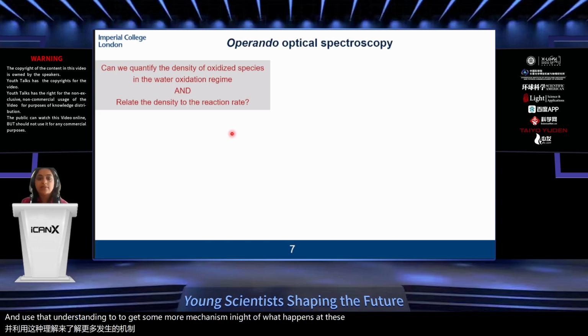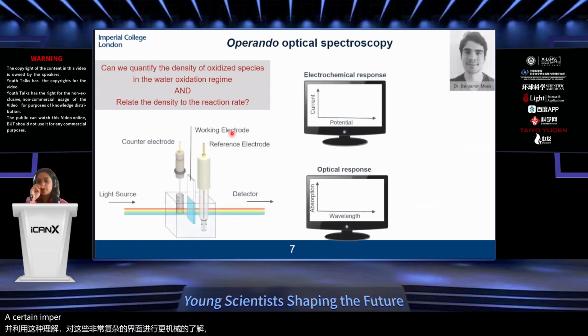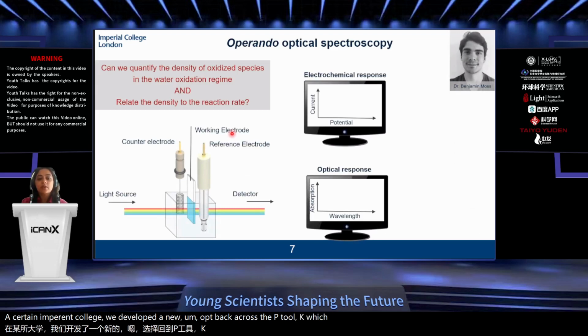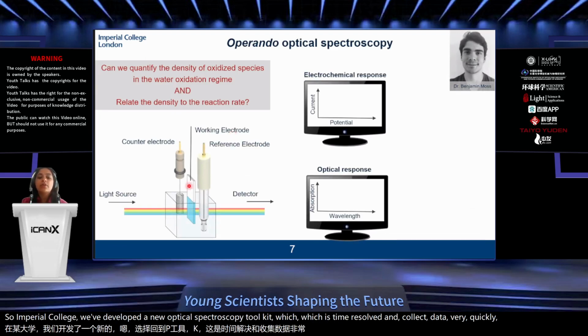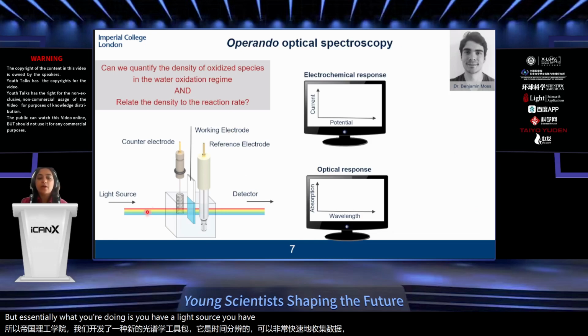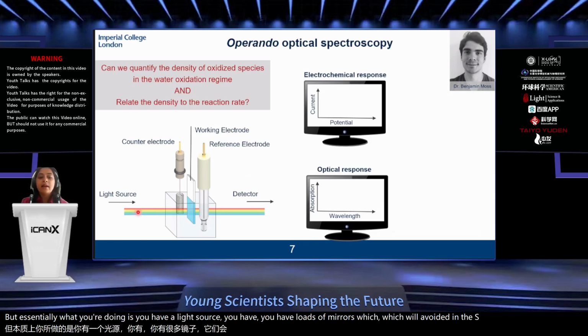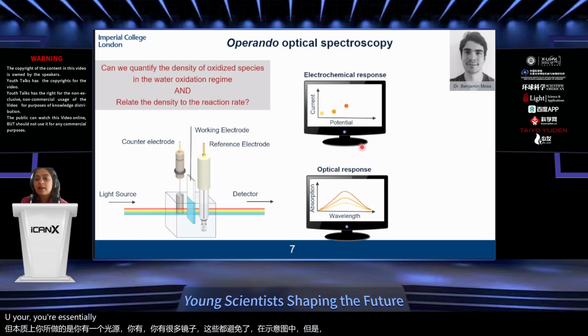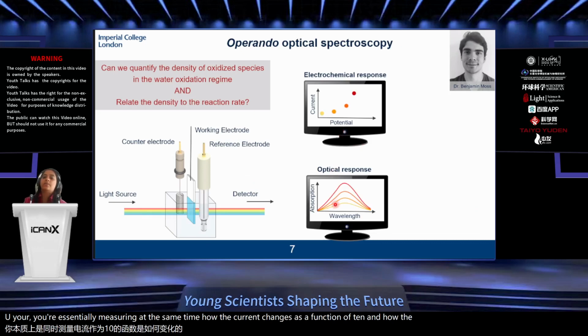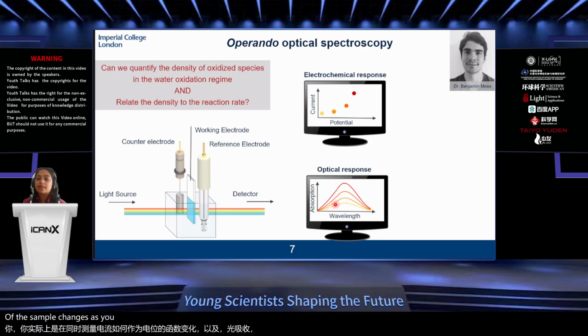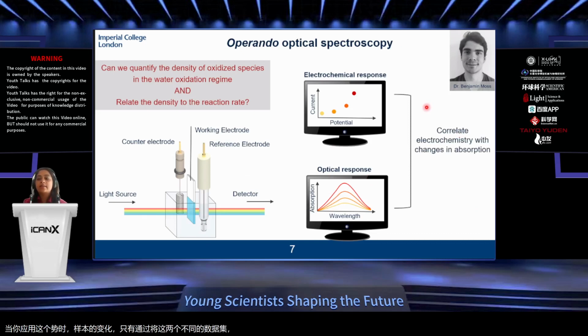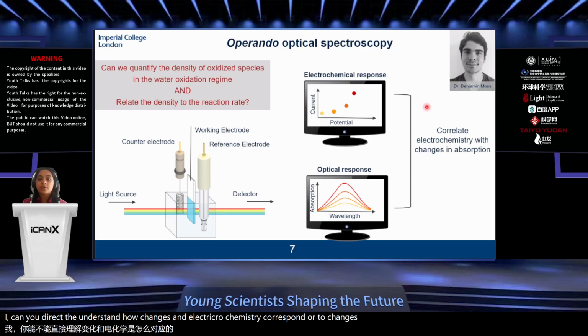So at Imperial College, we've developed a new optical spectroscopy toolkit, which is time resolved and collects data very quickly. But essentially, what you're doing is you have a light source, you have loads of mirrors, which I have avoided in the schematic, but you're essentially measuring at the same time how the current changes as a function of potential and how the optical absorption of the sample changes as you apply this potential. And it's only by correlating these 2 different data sets that you can directly understand how changes in electrochemistry correspond to changes in the optical absorption.